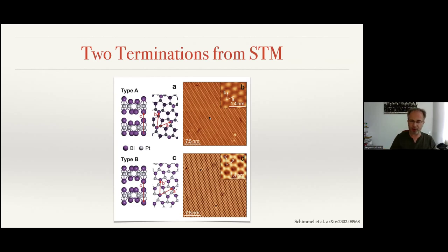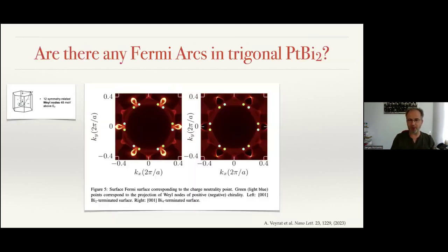This is quite a unique situation because most of the non-centrosymmetric materials grow with stacking faults, and depending on where you are at the surface, one could really see one type of termination or the other type of termination. So in this case, this is a unique material and very helpful for the experiment, because if you cleave it, if you open it in vacuum, then it will always be either one surface or the other surface. In order to study both, we cleave the crystal in air, flip another part and glue them together. So one could select which surface, A or B, to study.